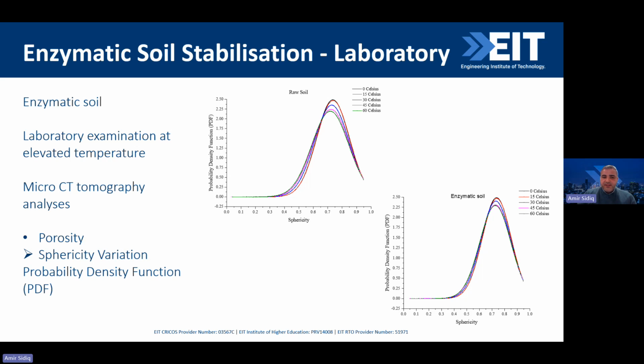So you can see here, the probability density is actually decreasing, and shifting from 0. The center of these curves is actually moving towards 0 as the temperature is increasing for the raw material, which really means the spherical shape of the pores is becoming less spherical. And definitely when you have less spherical, we're not actually looking at something good.